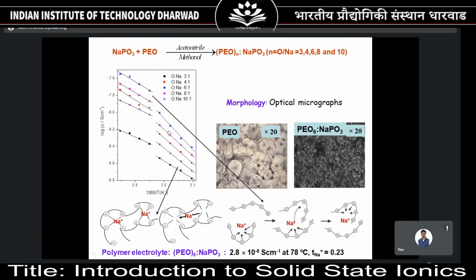Before it becomes free-flowing, the matrix was rigid, like this, which I am showing. After softening, the chains became very flexible, and they are giving extra support for the ion to move from one place to another place. So you have two ranges of temperature dependent conductivity: below the softening region and above the softening region.